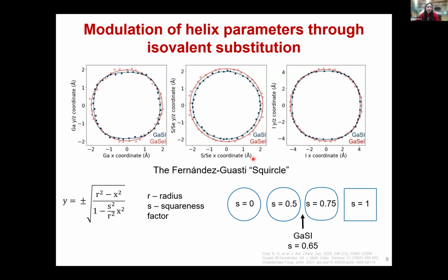While we saw that for the chalcogen site shown here, where the blue shows gallium sulfur iodide and the red shows the selenium one, for the gallium and iodine cross sections, we found that instead of contracting, they actually distorted. We were able to fit these cross sections to a shape known as a Fernandez-Guasti squircle, which is a cross between a square and a circle, with just one extra parameter in the fitting equation, S, that tells you how square or how circular you are. Gallium sulfur iodide lies appreciably between a square and a circle, with the S of the gallium and iodine being around 0.65.